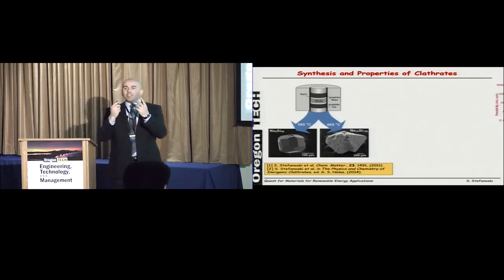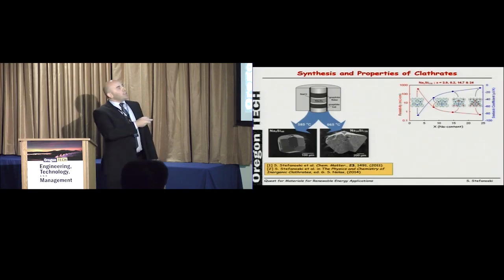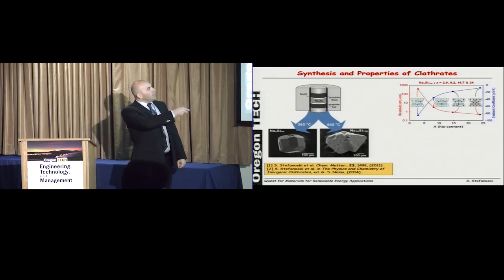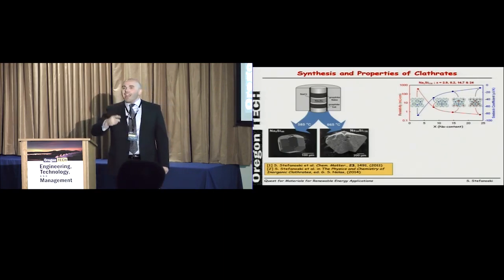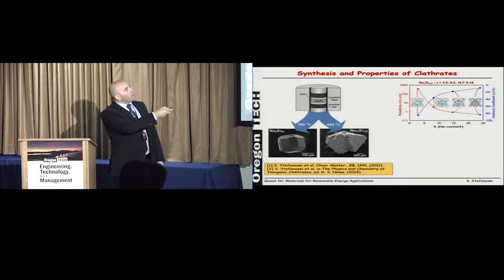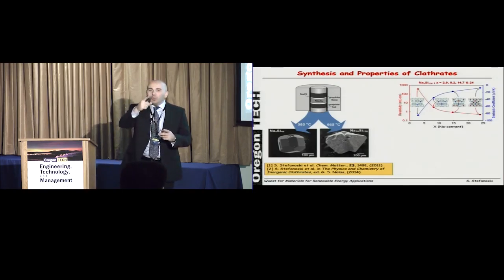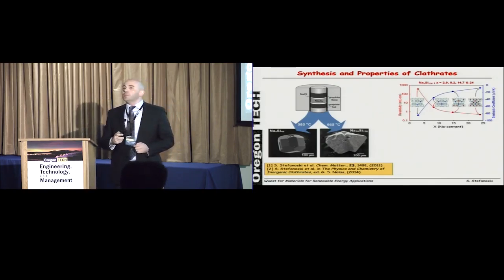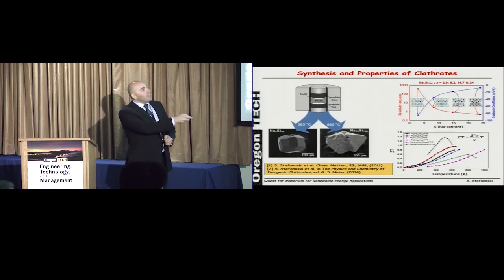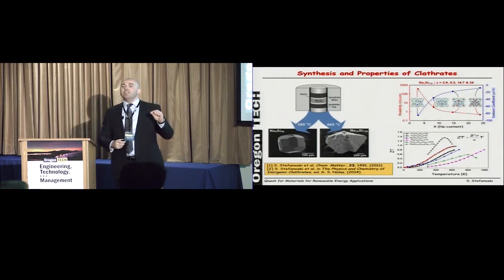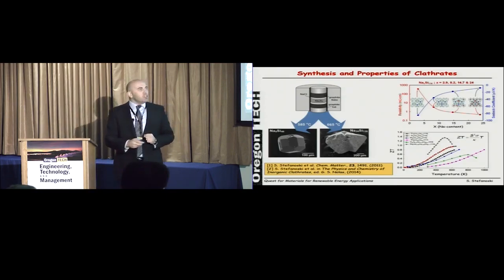What is the importance? What is the significance of these materials? Let's take a look at the electronic properties of this material as a function of the sodium content. This material has a variable sodium content. We can change the sodium content from fully filled, x equal 24, which is shown here, to almost empty, or x about equal 3. And as you can see, by tuning the composition of the material, we tune the electronic as well as thermal properties of this material, ultimately tuning the ZT value and finding a maximum ZT value, which is telling us whether that material will be beneficial for thermoelectric application.